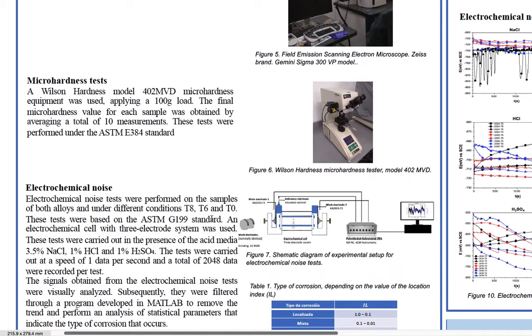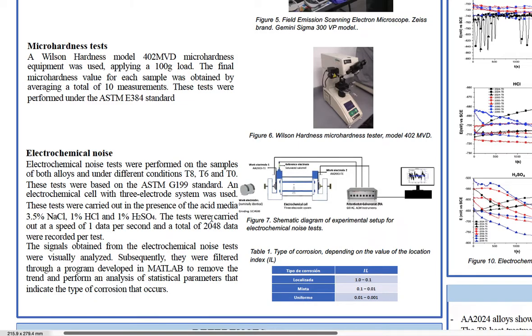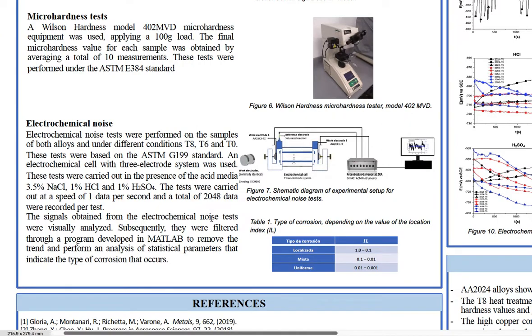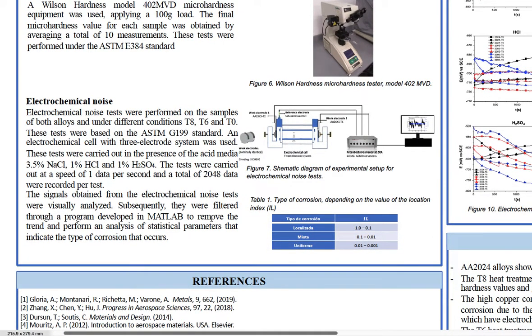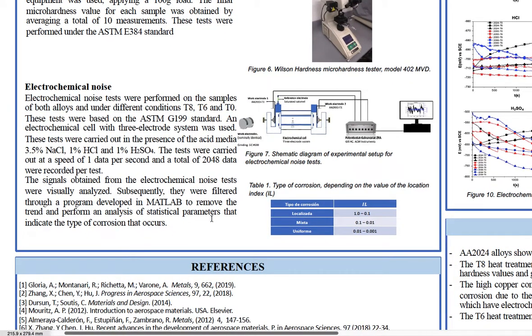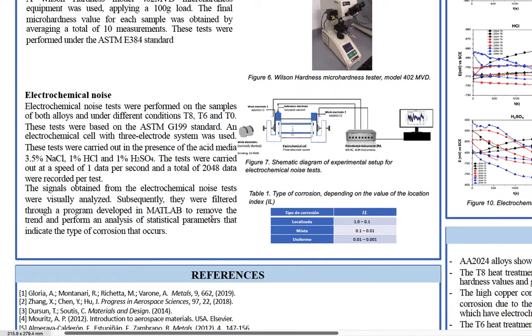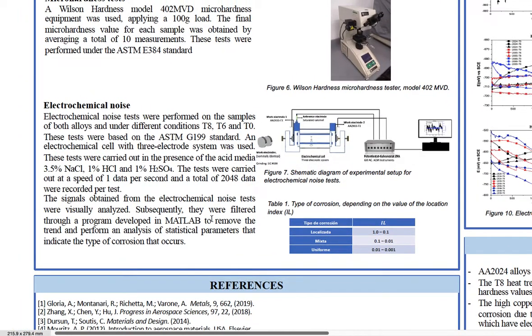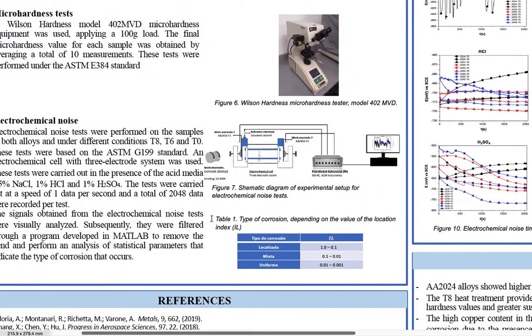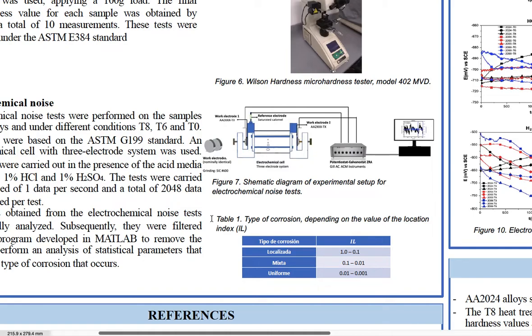Another group of samples in the three heat treatment conditions were prepared to be subjected to corrosion tests. The electrochemical noise technique was used. The tests were performed in the presence of three solutions: sodium chloride at 3.5%, hydrochloric acid at 1%, and sulfuric acid at 1%. The results of this test were analyzed visually as well as by means of statistical parameters. Here I show the schematic diagram of the experimental setup for this electrochemical noise test.